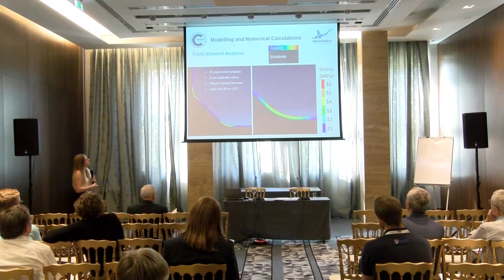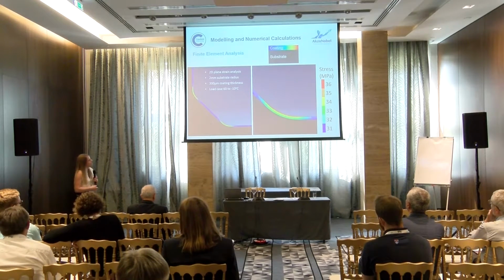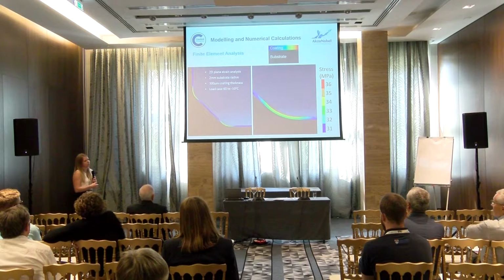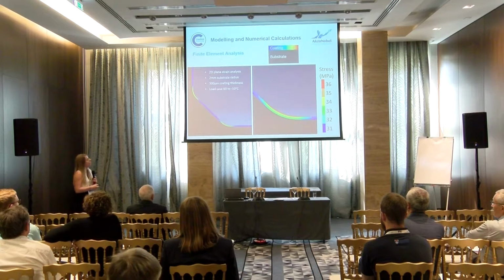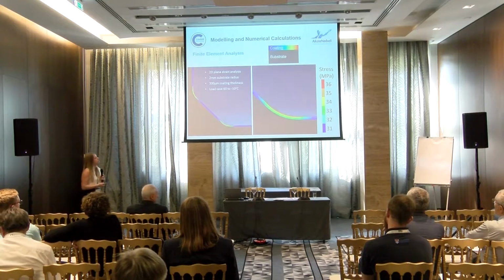So the image shows the stresses within the coating at minus 10 degrees C. So we can see very clearly that we're getting very high stress concentrations within the weld fillet area, and that the highest stresses will present at the surface of the coating. So these values can then be translated into thermal strains for comparison.